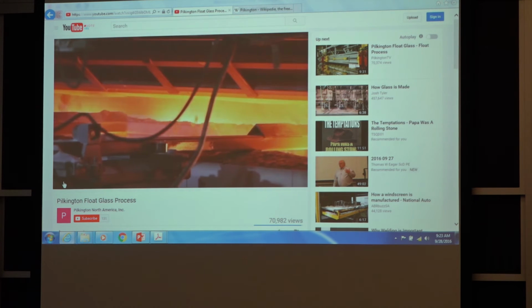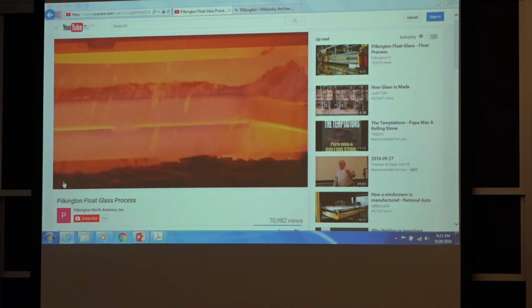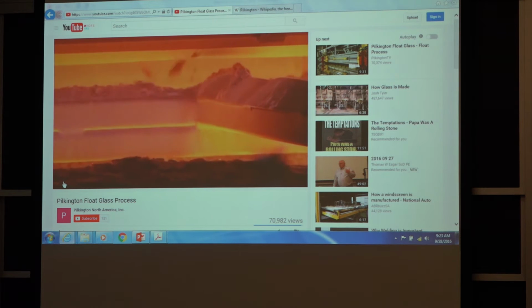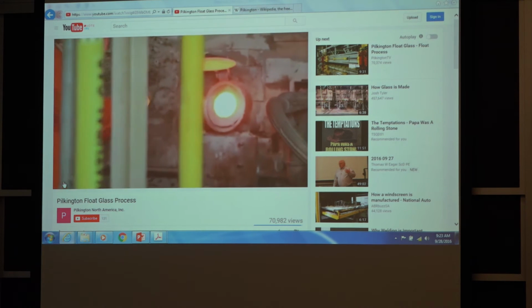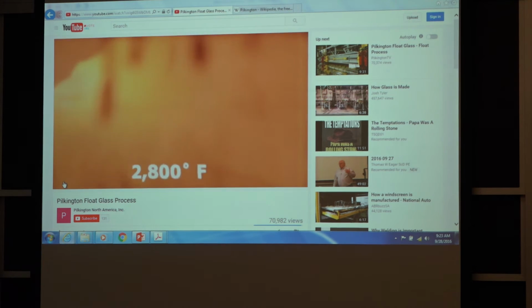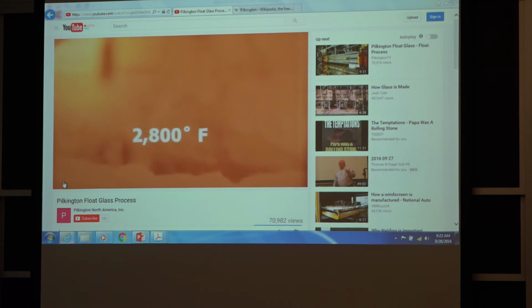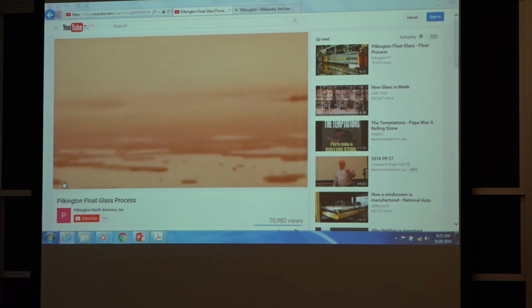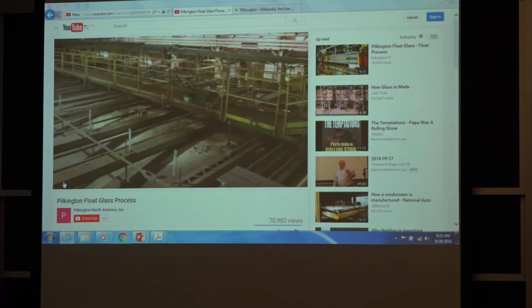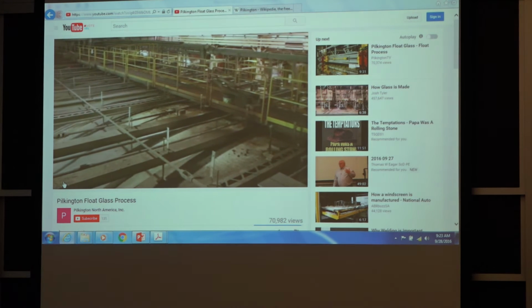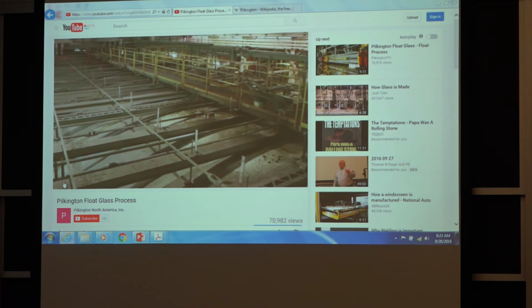If they don't get all the impurities out, we'll see what happens when we talk about the glass fractures. Natural gas burned in preheated combustion air then heats the batch up to 2,800 degrees Fahrenheit. Once heated, the batch materials melt and change from a semi-molten state to molten glass. Melting, refining, and homogenizing take place within separate zones of the furnace.